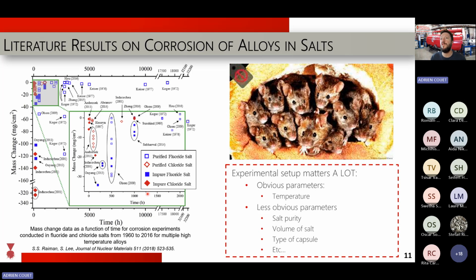Some of them are relatively obvious. In this plot, the temperature is not always the same. There are some variations, but not a lot. And then there are a lot of other parameters, salt purity, and so on. One thing that you can see in this plot is that usually impure salt, the filled symbols, shows a higher weight loss than pure salt. So really purity of the salt also matters.